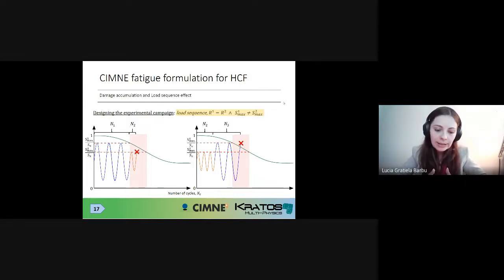It was demonstrated that the sequence in which different cyclic loadings are applied, so if you're in cycle 1, or if you are in cycle 2000, or if you're in cycle 200,000, the degradation level is not the same. It can be different. So it's important to have models that are able to account for the load sequence effect and for the damage accumulation effect. And in this sense, we have been working together with our colleagues at Eurecat, which is the Catalan Research Center, on designing an experimental campaign that can help us demonstrate that our model is perfectly capable of accounting for this load sequence effect.